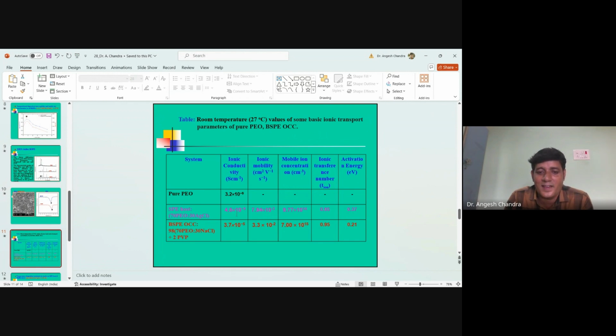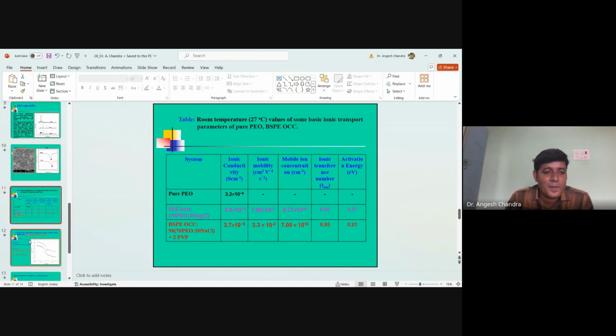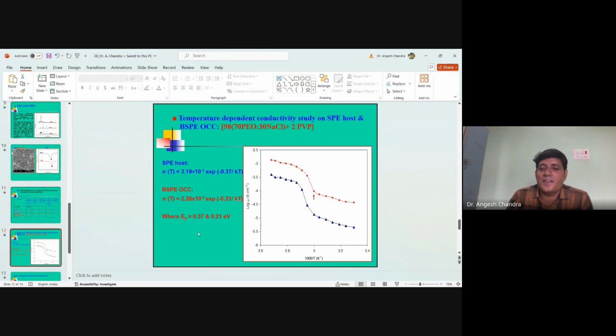We can see here clearly that the conductivity increases up to one order, and this increase in conductivity is due to the increase in both ionic mobility and mobile ion concentration, as well as the activation energy is also lower as compared to the SPE host salt. Now this figure shows the temperature dependent conductivity studies of SPE host and the BSPE OCC. We can see here as the temperature increases, conductivity also increases, and at this particular temperature, a jump in conductivity is observed. The jump in conductivity is due to the melting point temperatures.